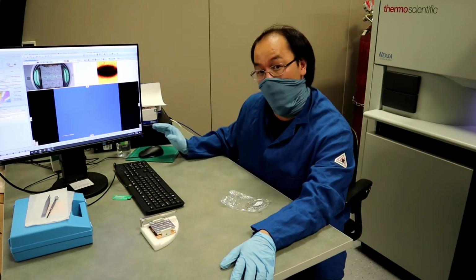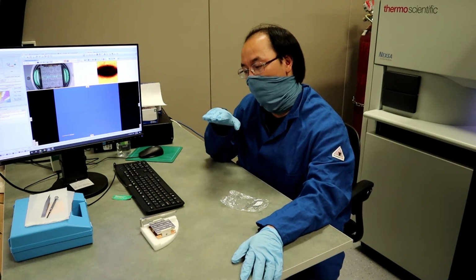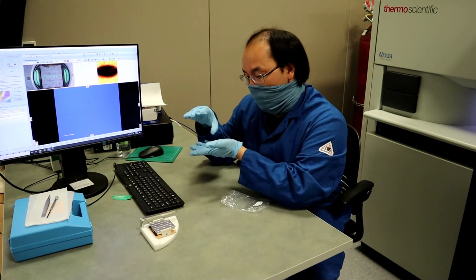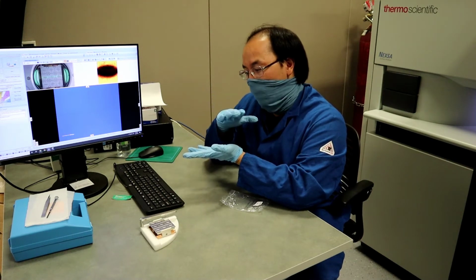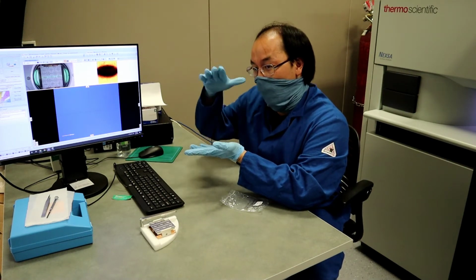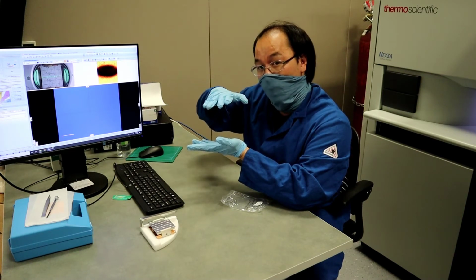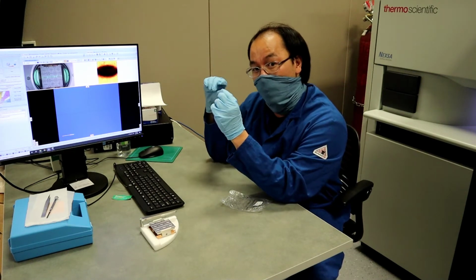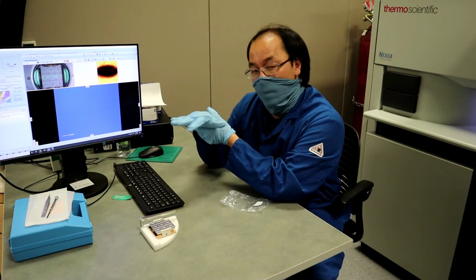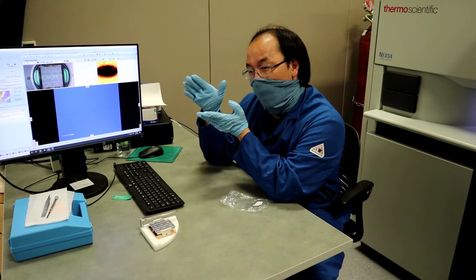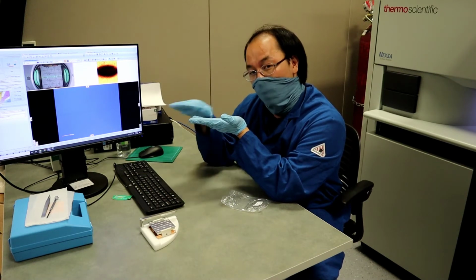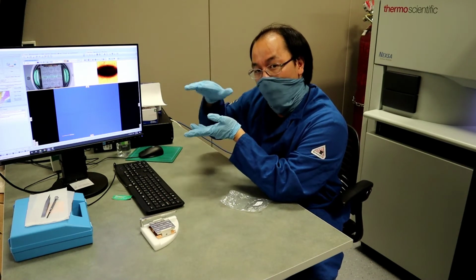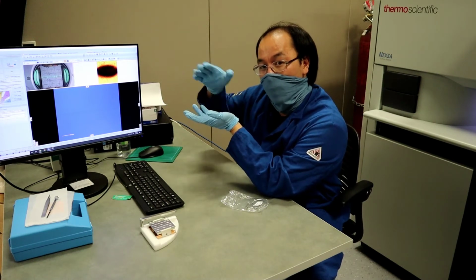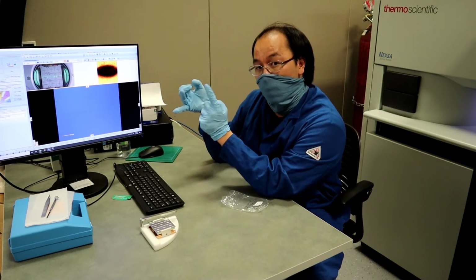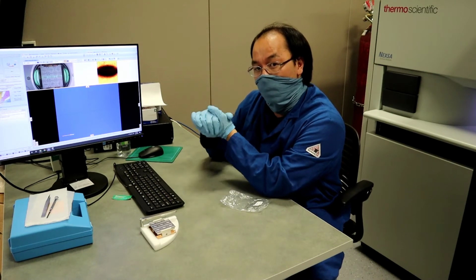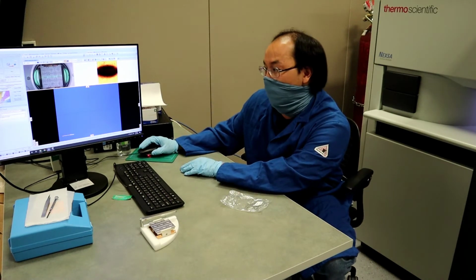For the ion gun, that is if you want to etch the surface to remove different layers. Say you have a sample and you're interested in if you did a certain treatment on it and you want to see how the top of the surface of the sample is different from, say, the top 10 nanometers versus the bottom 10 nanometers, so on and so forth, you would etch the sample, remove the first 5 nanometer layer, analyze the surface with X-rays, etch another layer, then you can analyze a depth profile of how your sample looks based on your treatment. You can see what kind of elements are present, what kind of potential bonds there are present as well. And that would be our XPS instrument.